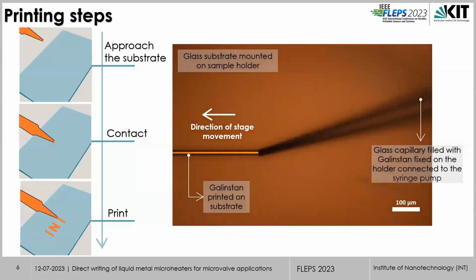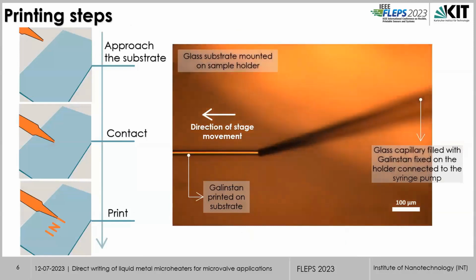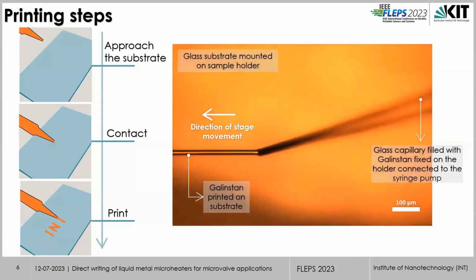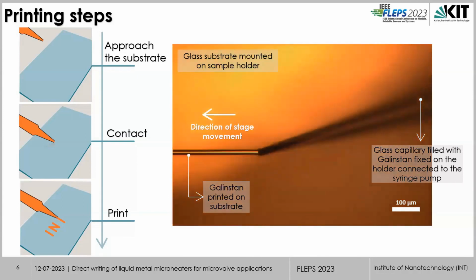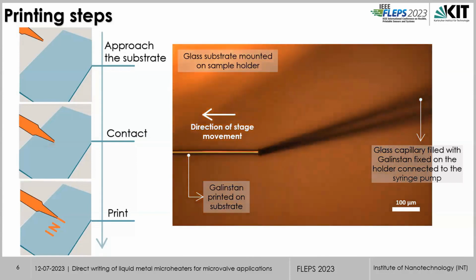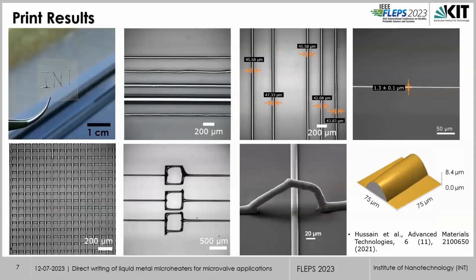This is the printing step. Once we know this is the pattern we want to print, we define it, and then when we start it, the glass capillary tip stays static, and the stage moves, and it comes in contact with the tip, and then it moves in the directions that are needed, and we have our pattern there. These are some of the print results. You can print in centimeter scale, different widths of lines, very homogeneous lines, and also different structures like this, and also freestanding 3D lines for the connections.